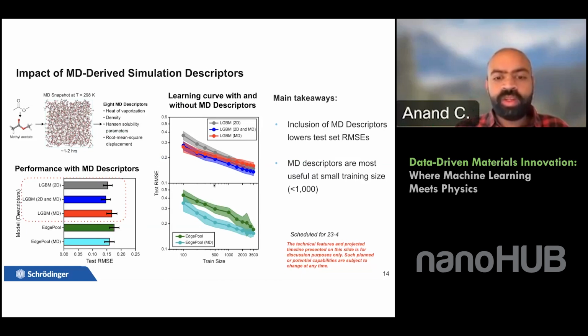And one very illustrative graph is shown here in the bottom right. You can see that the dark green line is the graph-based model for viscosity, whereas the cyan line is the graph-based model with MD descriptors. And we see that adding MD descriptors really drops the root mean square error for predictions of viscosity, especially when you have low data set sizes of less than 500 molecules.